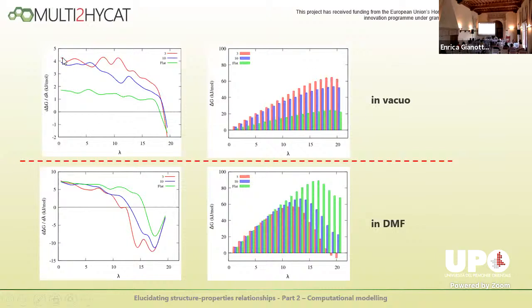Varying lambda, this is the derivative of the free energy along the path. I remember that the derivative of the free energy means the average of the V1 minus V0 inside this system. This average changes because at any step, lambda has a different value. So the molecular dynamics runs differently for any step because the interaction between the molecule and the silica changes continuously. But they are all molecular dynamics. For the rest, the calculation is always the same. What is changing is simply a part of the interaction between the two systems, the molecule and the silica.